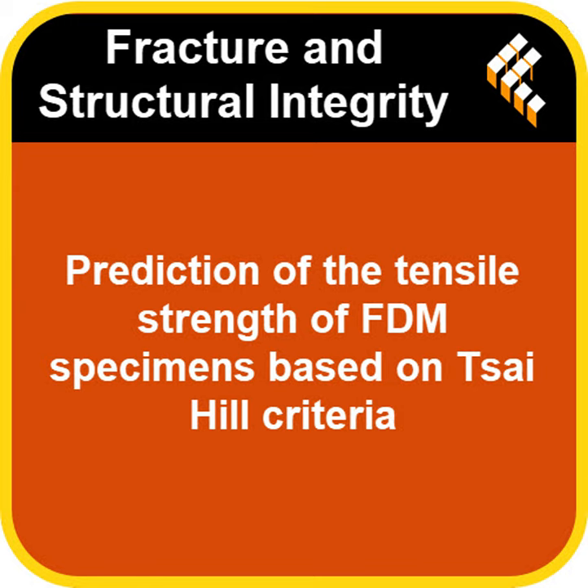And then there was the middle one, that 45-degree crisscross pattern. How did that do in the tug-of-war? The 45-degree orientation. This one actually had the lowest tensile strength. Lowest, yeah, lowest peak strength when they pulled on it, whether it had the contour or not. However, and this is a really key difference, these parts were much more ductile, more flexible. They stretched more. A lot more. They showed significant elongation before they finally cracked and broke.